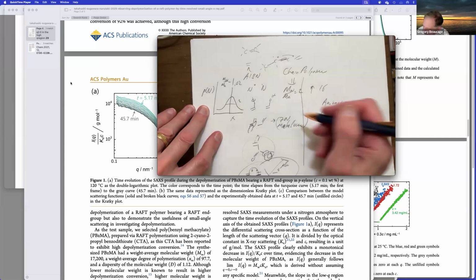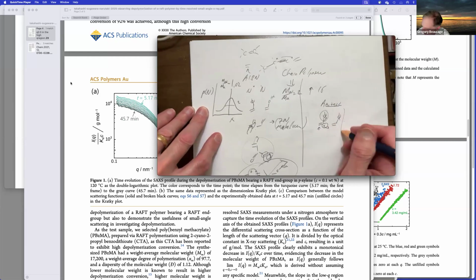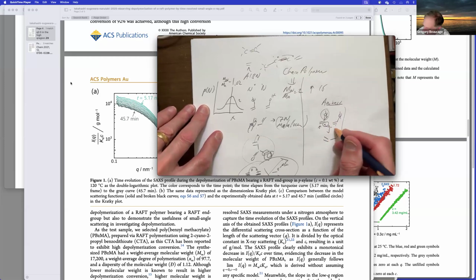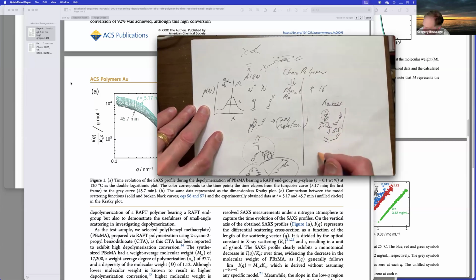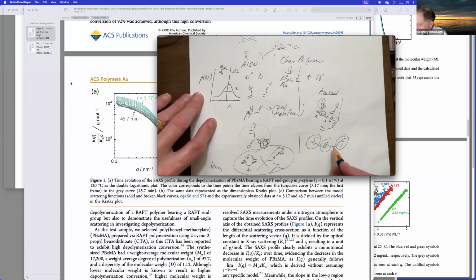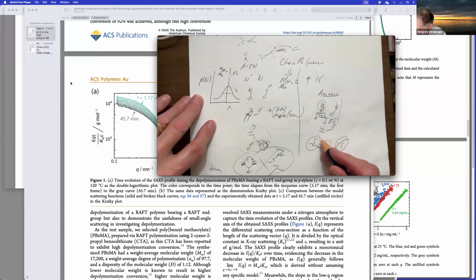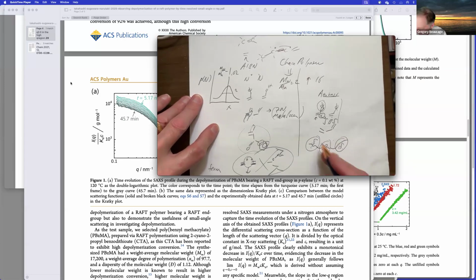One advantage of this anionic is that you can run it on polystyrene, and then you run out of styrene monomer. And then you can put in butadiene. So you can make a styrene, butadiene, styrene block copolymer. So like S and B, then S. Styrene makes a glass at room temperature, butadiene's liquid, so you have a thermoplastic elastomer. You can extrude it and it'll make a rubber. And if you heat it up, the styrene goes through glass transition, then you can extrude it. Or you can make tires from that.